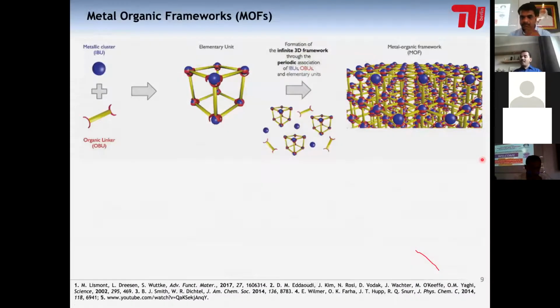So how do metal organic frameworks get synthesized? I have already said that metal clusters, you can pick any metal from the periodic table, start coordinating with linkers which have two types of coordination sites. The metal cluster starts coordination with the organic linkers, forming elementary units. In our language, we call it a secondary building unit, which extends into three dimensions, giving metal organic frameworks which are porous, crystalline, and have various functionalities in their backbone. Since these materials are made from metals, you can use these metals for catalysis. You can put functional groups on these linkers, and you can have functional linkers which can be used for various applications.